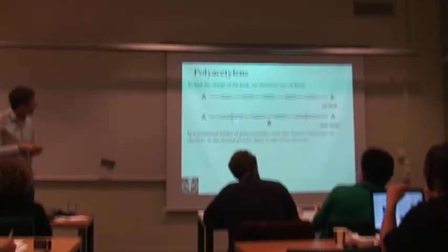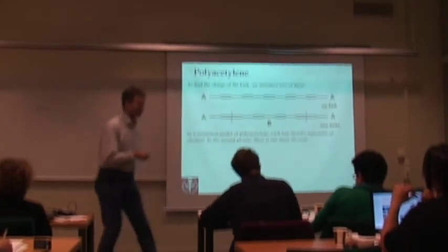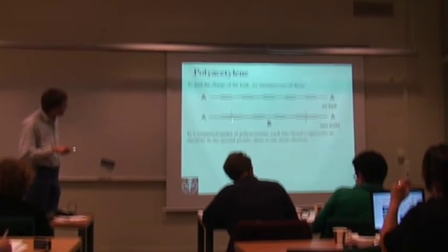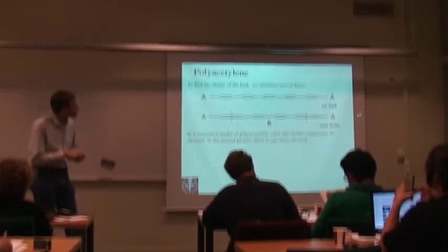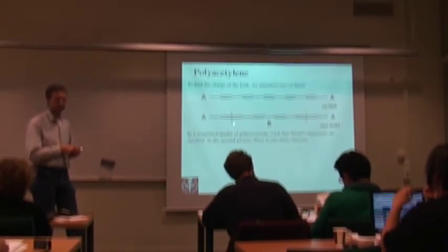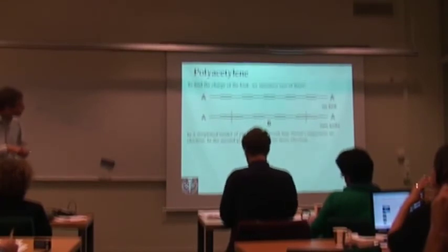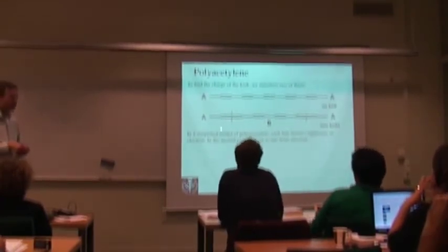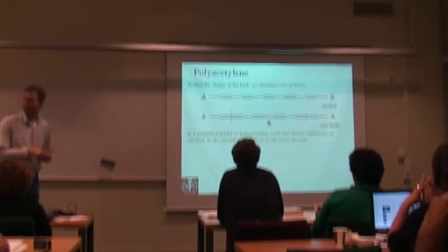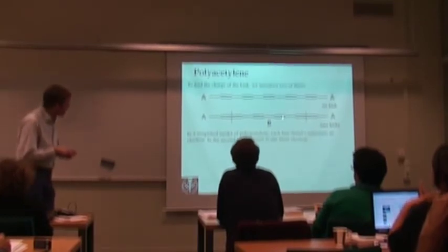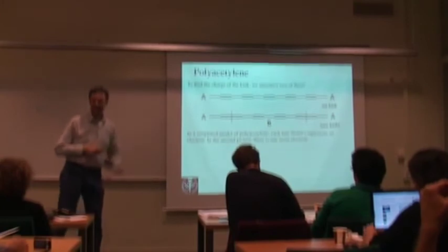So we created these kinks, and these kinks can just move around freely. They're like charged particles which can move around, like normal particles can. They just hop. We created two kinks here, so there's some charge here and some charge here, which can move around freely. If I do the counting, I see that in this system I have one charge more than in this system. If I call this the normal charge, or no charge at all, then I've put in one more electron here, so the total charge of this system is one. Now I've created two kinks and distributed the charge I added equally over these two. Because I only added one charge and distributed it equally, the charge here is a half and the charge there is a half. And I can only do this, of course, if I have many electrons. If I just have one electron, I can't do this.